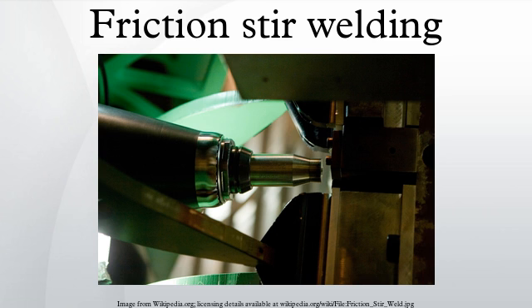Flow of material. Early work on the mode of material flow around the tool used inserts of a different alloy, which had a different contrast to the normal material when viewed through a microscope, in an effort to determine where material was moved as the tool passed. The data was interpreted as representing a form of in situ extrusion where the tool, backing plate and cold base material form the extrusion chamber through which the hot, plasticized material is forced.